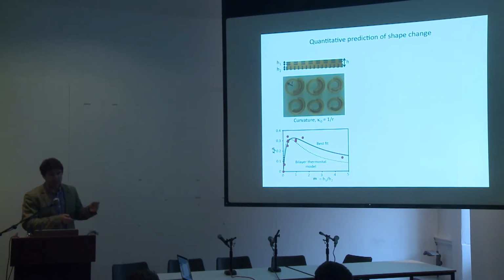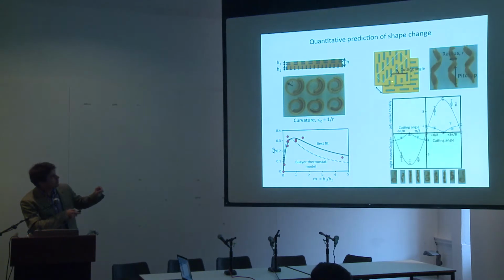Of course, now if we talk about programming the shape change, you also have to connect initial parameters of your structure, like the relative thickness of these layers, or the cutting angle, with the final structure or geometry that you get. In the case of bending structures, this would be the radius of curvature. In the case of mixed shape change, you would have the radius and the pitch. And I won't go into details, but we are able to nicely predict these final geometrical parameters based on initial properties of your composite.